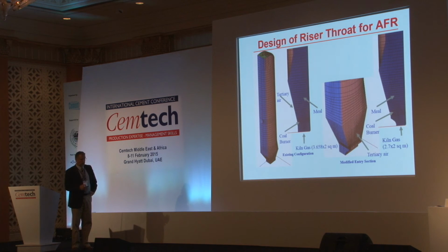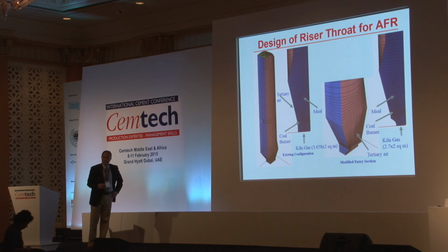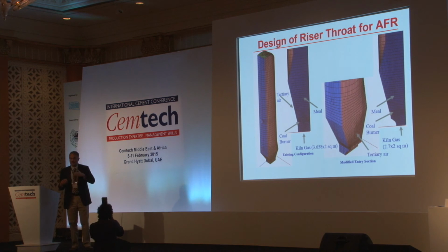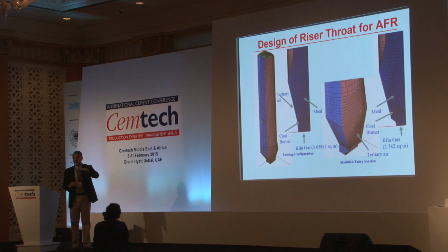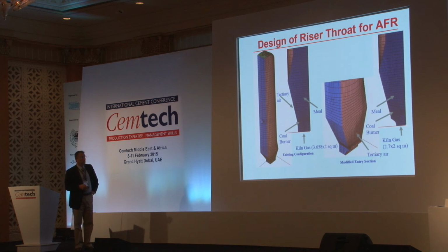So that's the computational grid. I won't go through the details, but in this area, a venturi was added there to have minimum pressure drop and higher velocities in the localized area, because the falling chips have to be decelerated, and after reaching zero velocity or the stagnation point, then after losing weight, losing volatiles, and burning, they would be lifted up. And then we can go to higher substitution.